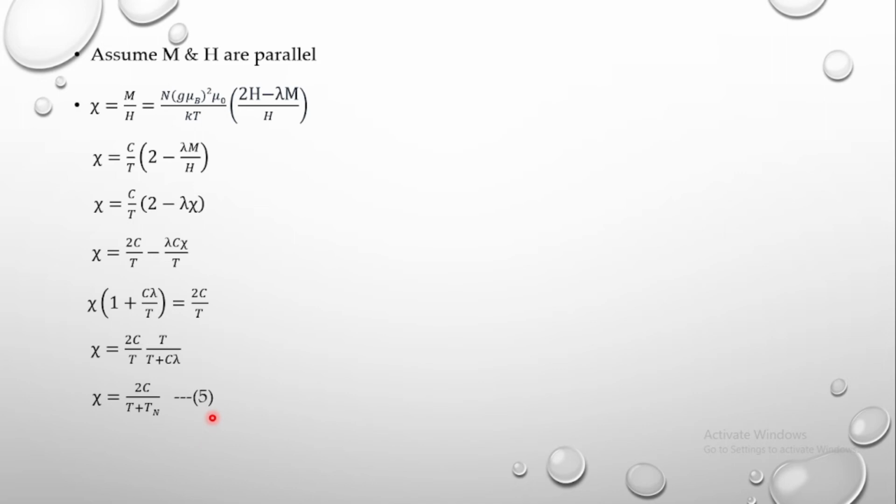So if you remember what we had studied in molecular field theory of ferromagnetism, we can say that there is a slight difference between the susceptibilities above the critical temperature. For ferromagnetic material we had chi equals C by T minus Tc, and here, instead of C, we have 2C, that is, the Curie constant is twice, because the constant of an individual A or B lattice is considered here. So 1C corresponds to sublattice A, 1C corresponds to sublattice B, and instead of T minus Tc we have T plus Tn.